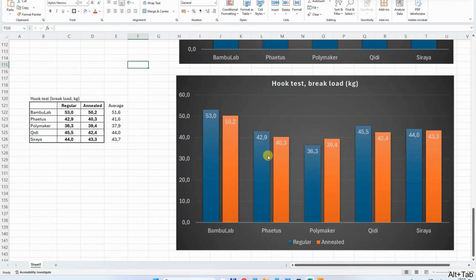On this graph we can see annealing didn't really change the mechanical properties of these hooks. In most cases it's even a little bit weaker, except with the Polymaker. Here we can see some improvement, but the difference is negligible.